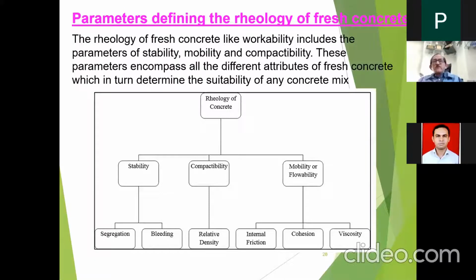The rheology of fresh concrete, like workability, includes the parameters of stability. These three parameters we call SMC, or stability, mobility, and compactability. Here I have written stability, compactability, and mobility or flowability. All these three parameters encompass the six parameters in turn. The stability of the concrete will depend on whether it has segregation resistance and whether bleeding is present or not. If bleeding is present, then we would say the concrete is not stable. Then compactability will depend on relative density and how easily it can be compressed or put into the formwork we are using. Then mobility will depend on internal friction, cohesion, and viscosity.